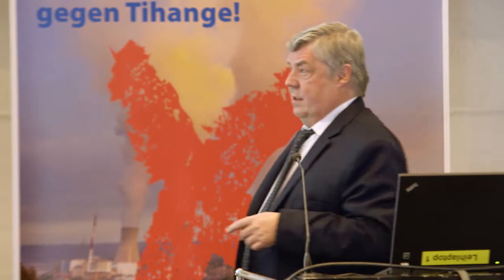But these are typically spherical cracks. It's a known phenomenon from the 1960s, these hydrogen flakes, almost spherical, but in fact hydrogen-induced brittle fractures. Now, fortunately, it was detected that most of these were laminar or quasi-laminar along the vessel wall, which is fortunate, of course, but there were some high densities, and I will show you later what being laminar or quasi-laminar along the wall means with some practical examples. So, can they grow? These hydrogen flaws.